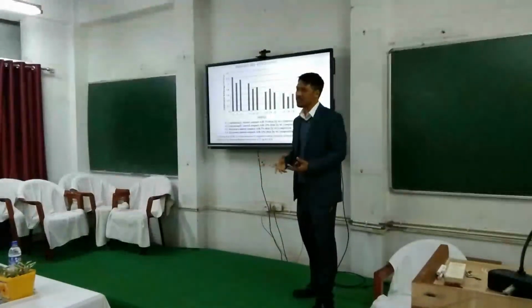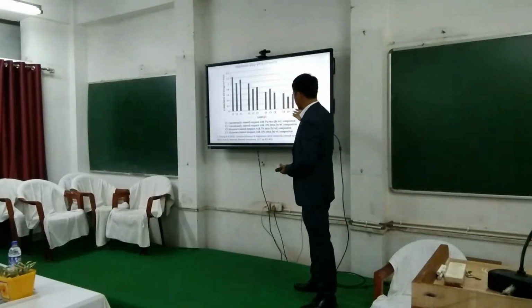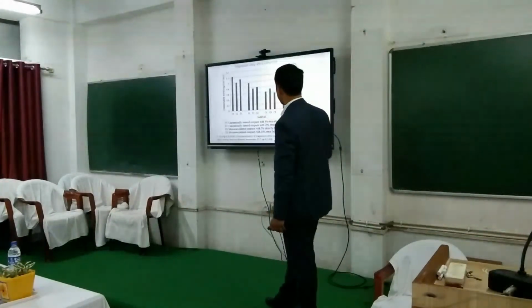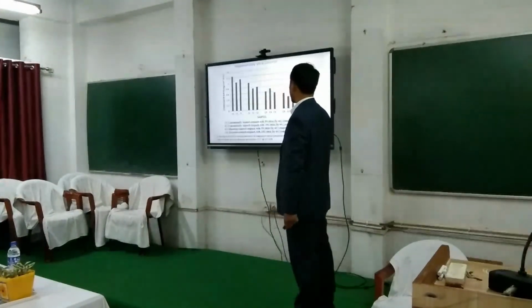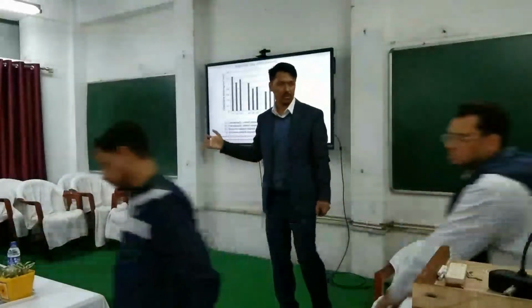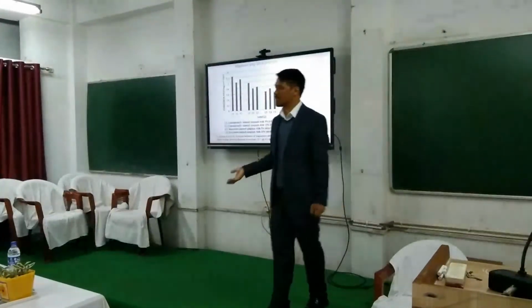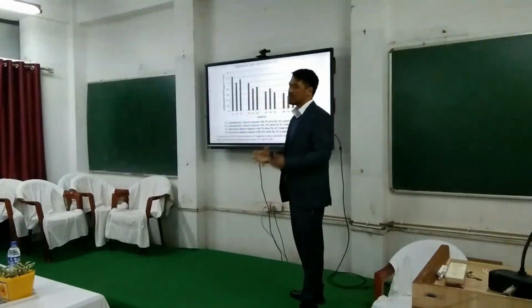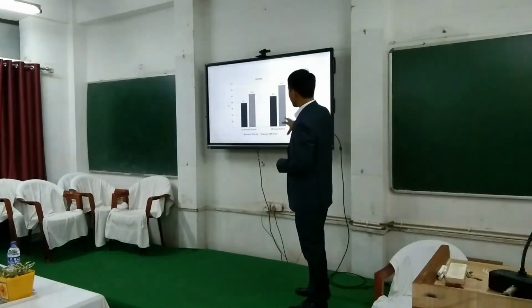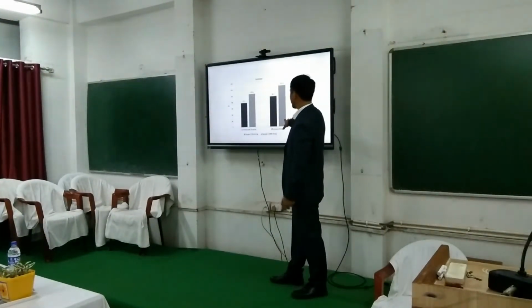Some years back I did some research on magnesium alloy composite formation by microwave heating, and these are some results from those times. If you compare conventional sintering and microwave sintering, the conventional sintering has more corrosion, so corrosion resistance is checked here. Microwave sintering compacts have very good corrosion resistance. The reason for this is that we are getting very small grains in the microwave heating. You can see how with change in these different processes, even the hardness has improved.